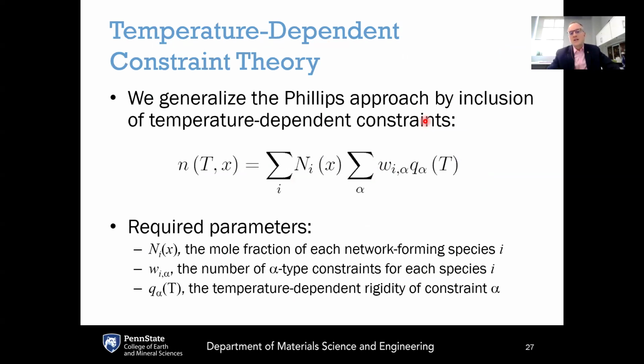Now, Phillips's theory was a zero temperature theory, and if we want to apply this to systems at finite temperature and to predict how properties are evolving with composition and with temperature, we need to generalize this. And the generalization of this theory was developed by Prabhat Gupta and myself, and it's called temperature-dependent constraint theory. And the base equation here for temperature-dependent constraint theory is that the number of constraints per atom, this little n, is a function of the temperature of the system T and the composition of the system X.